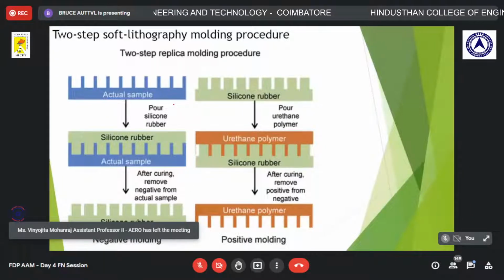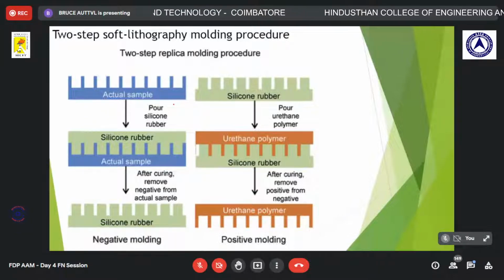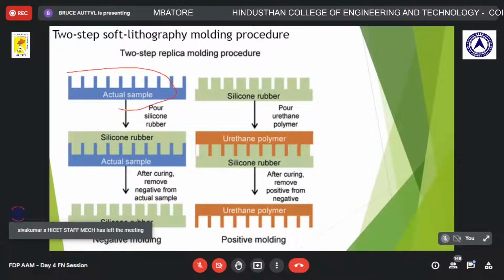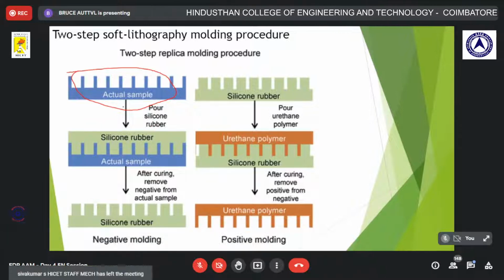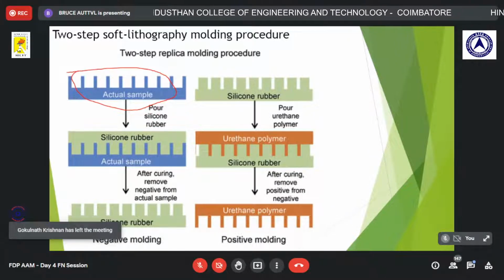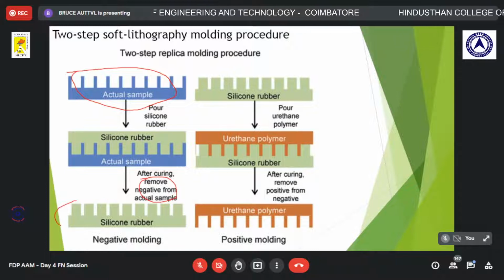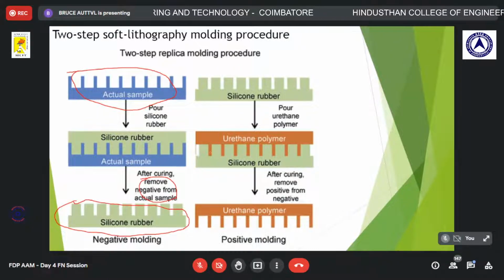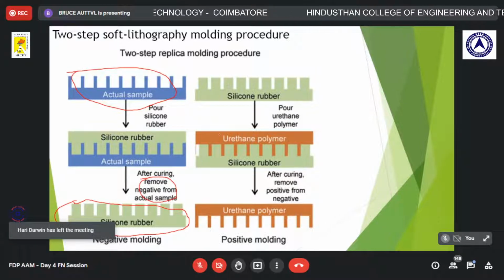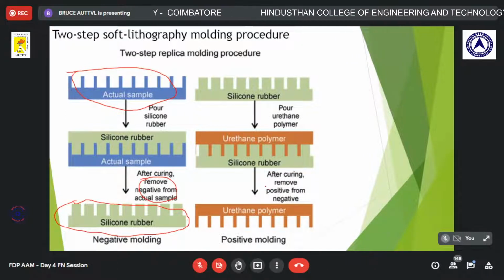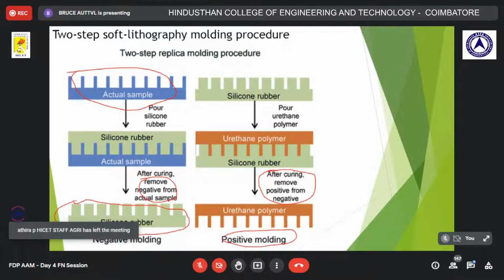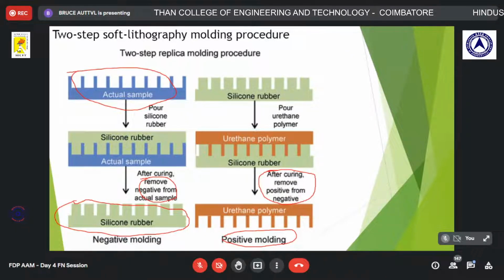Okay, you can observe the soft lithography molding procedure, which is a famous technique. So in this, this is the actual sample, and over this actual sample, silicone rubber is poured, and after curing, remove the negative from the actual sample so that your negative molding, that is your silicone rubber negative molding, is prepared, and pour urethane polymer over it. So after curing, remove the positive from the negative so that the positive molding, the urethane polymer, is obtained. So this is a two-step soft lithography molding procedure to prepare the bioinspired structures on a macroscopic scale. That is very important.